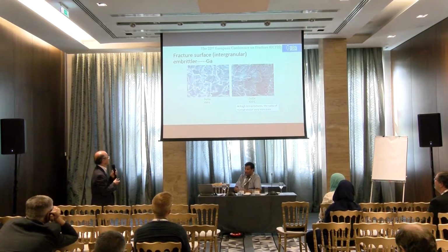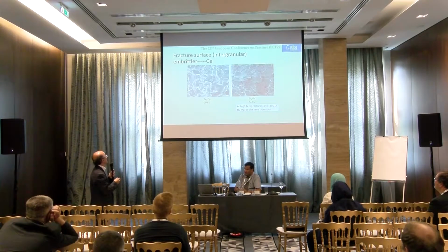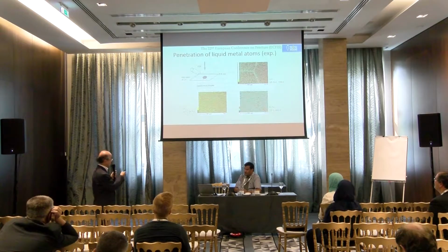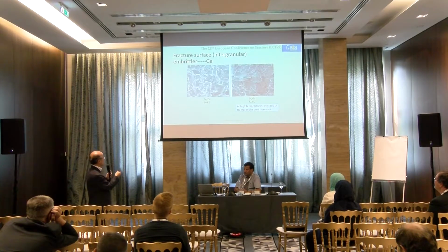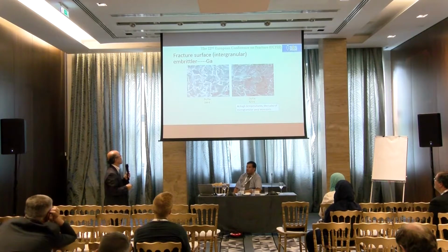Now the fracture surface. In the case of gallium, the fracture surface is apparently intergranular. At high temperatures, the transgranular region increases a little bit.